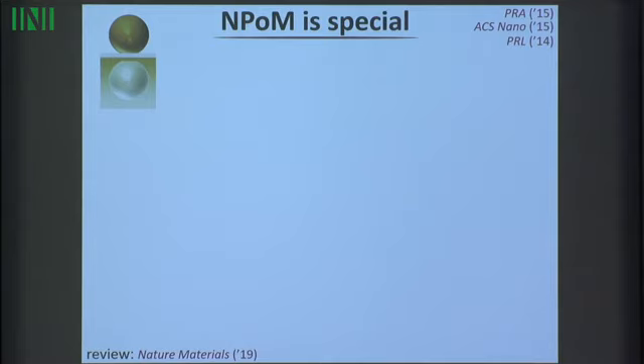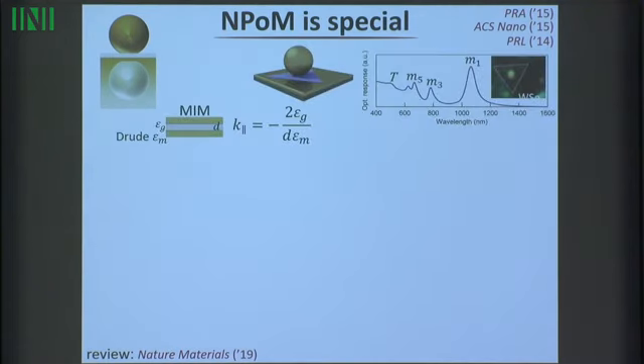If I take this particle and I put it onto a ground plane, then essentially all the charges here have image charges below. So any dipole here has an image dipole. So in fact, this system behaves identically to the single dimer. We've used this a lot in our labs. So for instance, we take a gold mirror, we put a very thin sheet of material upon it, and we put a gold nanoparticle on top. And the light gets trapped into this very tiny gap, but only a particular color of light. In this particular case, it's a yellow color that sits underneath here.